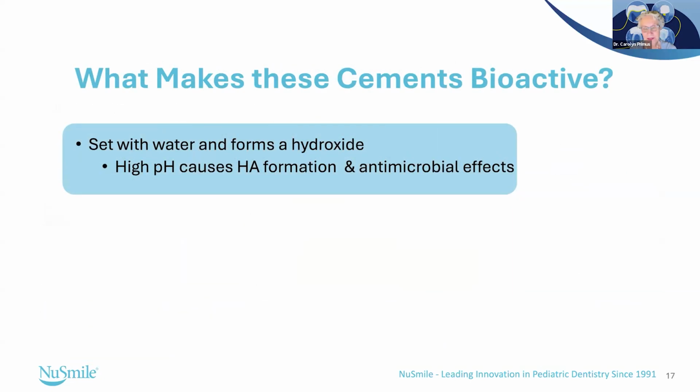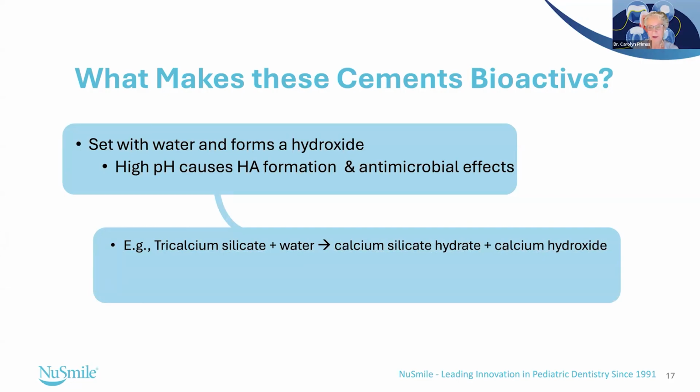So, what makes these calcium cements bioactive? They react with water, they form this calcium hydroxide, you get this high pH that causes the hydroxyapatite layer to form, and you get some concomitant antimicrobial effects because of the high pH.